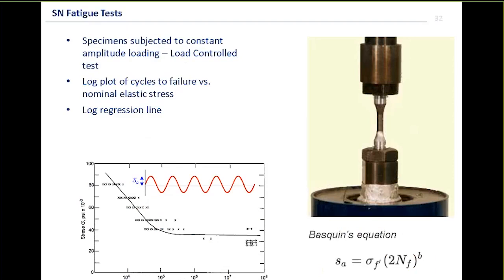So in this case, if we were to look for a typical rig set up for load control, we actually see that it's a specimen like this hourglass specimen. We give it a command waveform. We can see here that we've got a sinusoidal stress profile. And what we try and do is plot the number of cycles to failure on log axes. And we see here, if we start to look at that, we can start to see this straight line forming through there. And we can represent that using a simple equation. This is the Basquin equation. It's the equation of a straight line in log space.